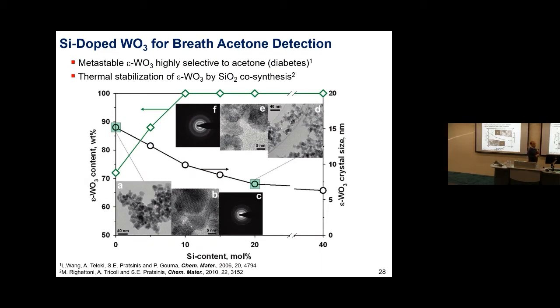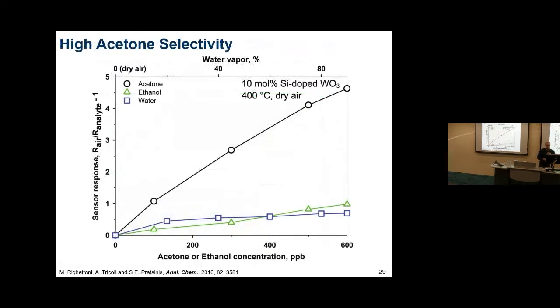If you're able to produce the right type of nanoparticle - for example, we discovered that silicon-doped tungsten oxide can stabilize the epsilon phase through doping. This phase is very selective to acetone. You can see here the response to acetone down to small concentrations, parts per billion, compared to the response to water and ethanol, where water at high concentration is much, much lower.